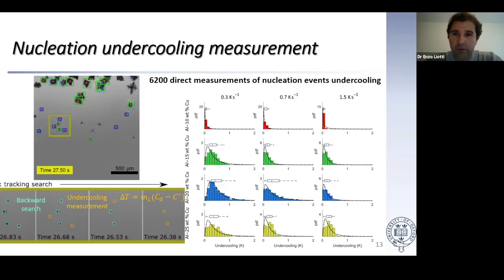Again, very interesting results, correlated like before as a function of the cooling rate and the solute content. And the behavior is in a certain way expected. Undercoolings are very small, as is known from theory. And so that's a confirmation of much of the theory.